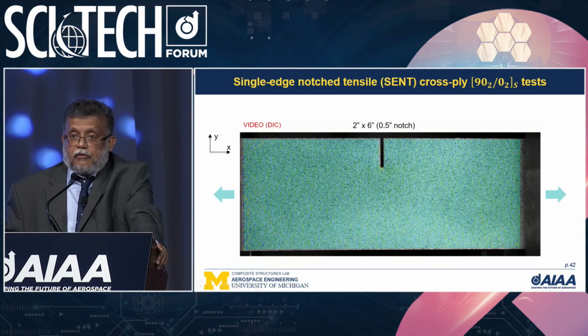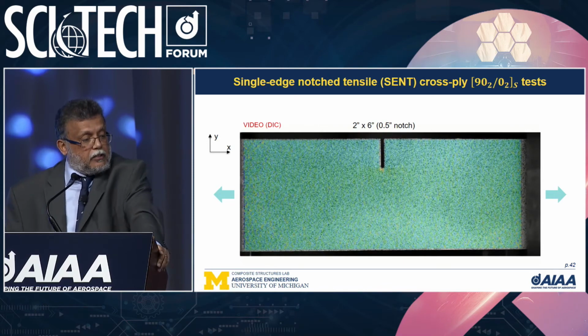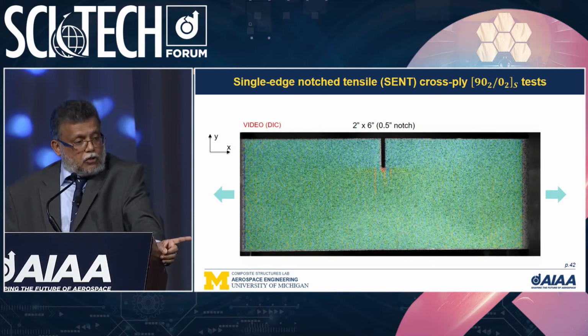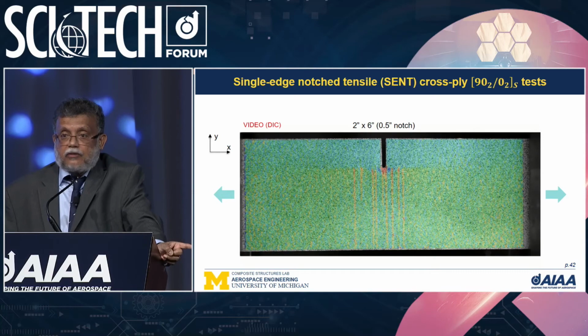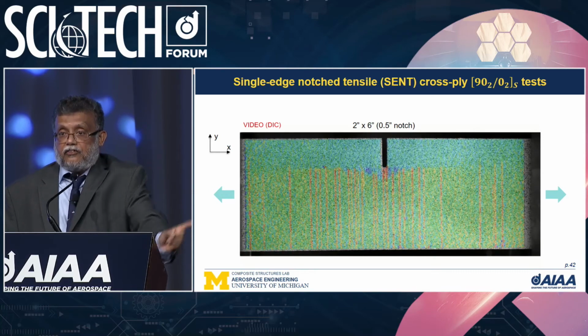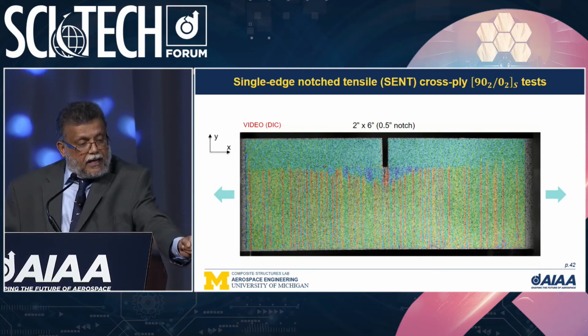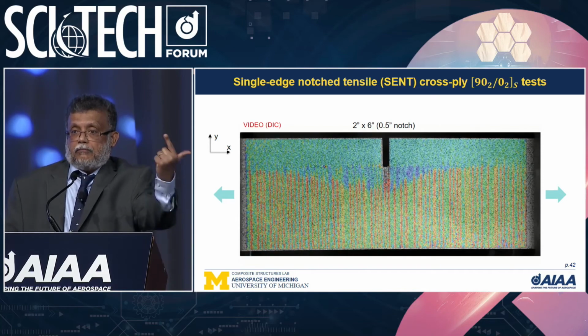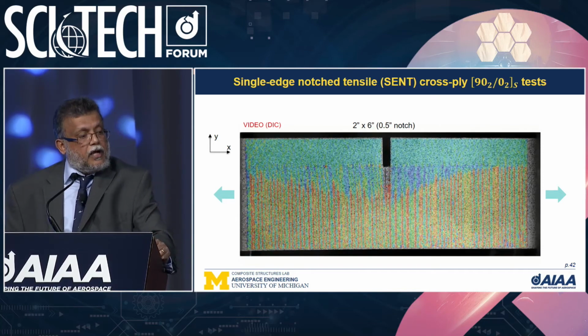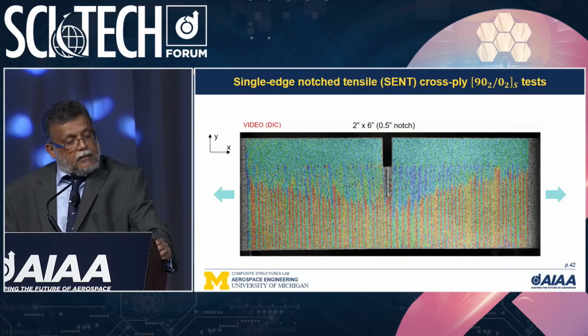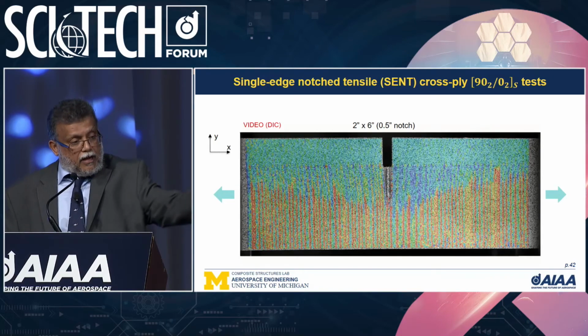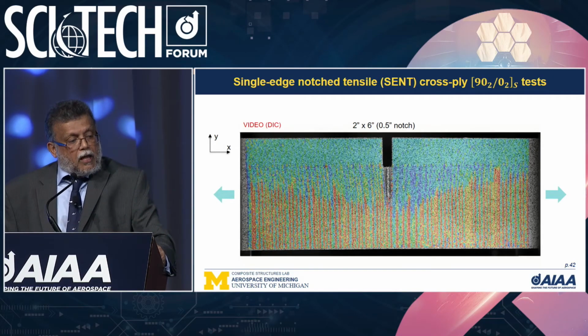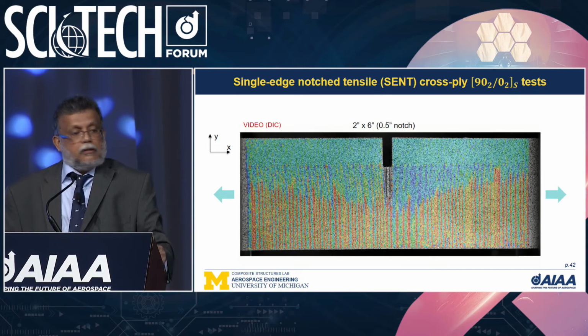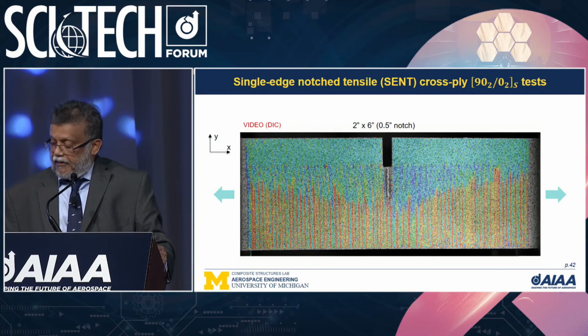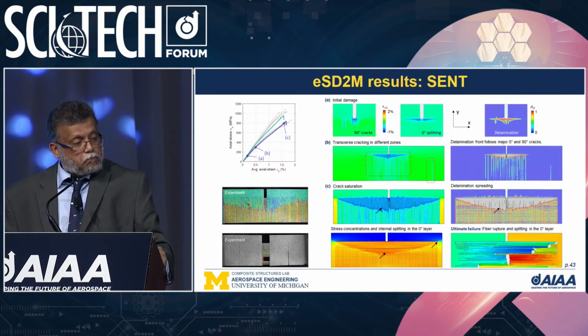So what happens when you pull it is you get notch localization, and you get splits going down the 90 plies. These are DIC results, and you get edge cracks coming from the bottom away from the notch and going up. Finally, you get delamination in a triangular region, and then you get rupture because the zero fibers fail, which I'm going to show you next.